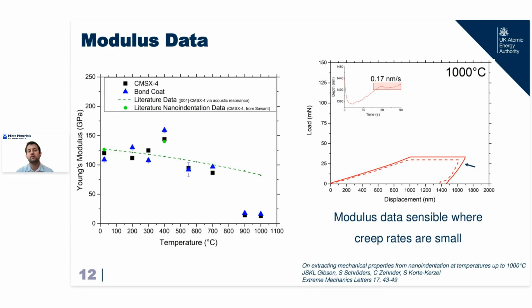There is too much creep left in our unloading curve, even after a very long dwell period, even unloading as fast as we can. In fact, we worked out that if we want to unload fast enough to beat creep in this, we need to be unloading at 300 millinewtons a second, which is far too fast for our electronics to keep up. We get no data in our unloading curve in that case.